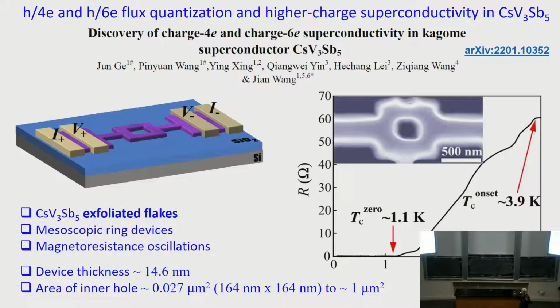But things do not look like Little-Parks oscillation at all, because you look at the transition now. It's so broad. This is resistance versus temperature. This is the zero resistance state. And this is the onset of superconductivity. Such a broad transition region. And there are features in them. That's really good news. There's some stuff going on in there.